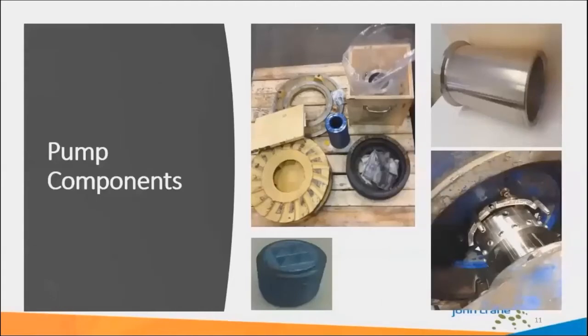the true pump hardware experts are, of course, the pump OEMs, and this is where a healthy working relationship with these companies proves its worth. I have made a few general observations with regard to how slurry pump design may affect mechanical seal performance. One in particular is sleeve material. It's standard practice to replace the old worn packing sleeve when you're converting to a mechanical seal. Just make sure that your seal supplier cares about your sleeve material. Trying to attach your nice new seal to a high chrome, super hard pump sleeve with soft stainless set screws is a recipe for disappointment.